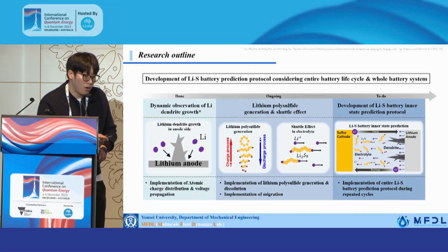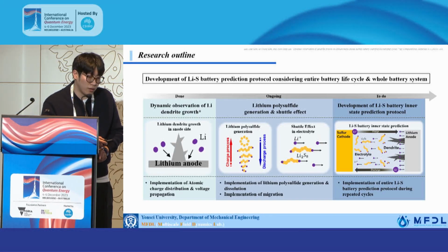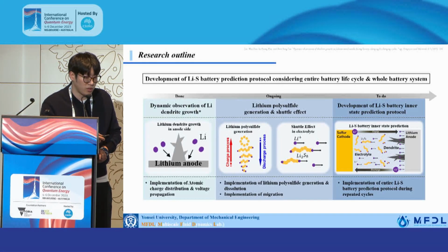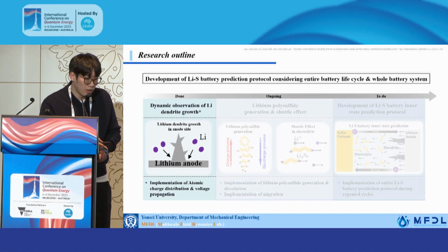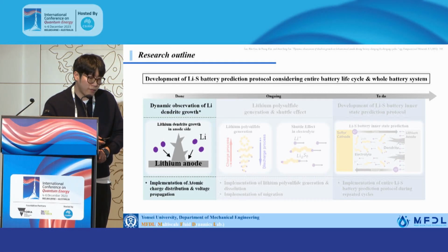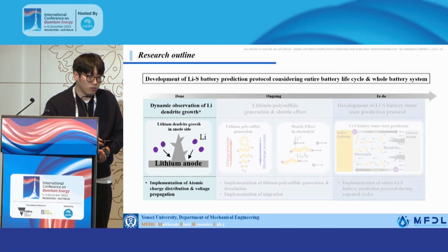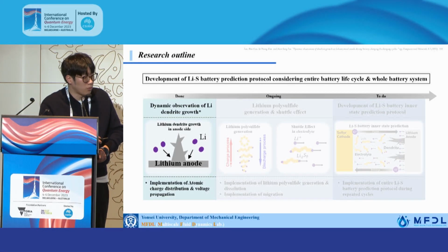So I would like to develop a lithium-sulfur battery prediction protocol considering the entire battery life cycle and whole battery system. In a previous study, I have already published a paper that introduced the computational protocol that provides a quantitative characterization and dynamic observation of dendrite growth. In this study, I implemented the atomic charge distribution and voltage propagation. And by using this method, I would like to expand this study with sulfur.